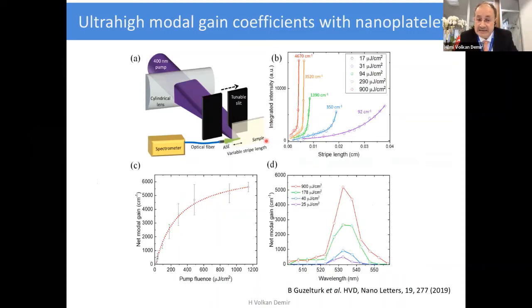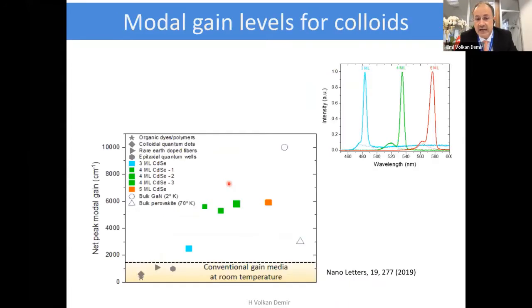And this is the highest net modal gain, so the gain capability of these materials. To put this in perspective, you can see the best results ever reported in the literature in their class: organic dyes, polymers, colloidal quantum dots. This is what we have worked on ourselves as well. Rare-earth doped fibers and epitaxial quantum wells are more conventional. They all reside here at room temperature. And these are the levels of gain one can induce using this type of atomically flat nanocrystals.